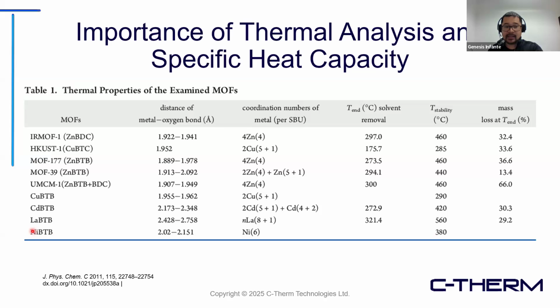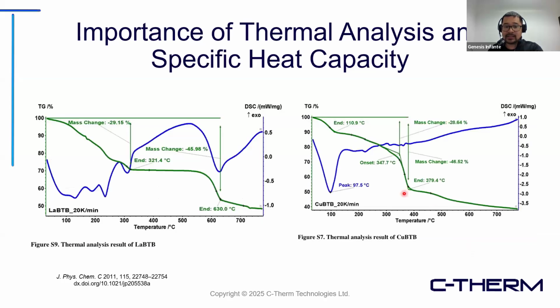And you can see here that this lanthanum BTB is the top performer versus something like a copper BTB right here, which has a thermal stability of only 290 degrees C max. And you can see that in these TGA DSC graphs. In this graph, in green is the TG graph, and the x-axis is the temperature. As you're heating up the system, you can see that there is associated mass loss. And then at some point that mass loss stops, and you have a stable region right here. Then you'll see a drastic decrease again beyond about 560 degrees C for this particular MOF. And the one in blue is essentially the DSC signal.